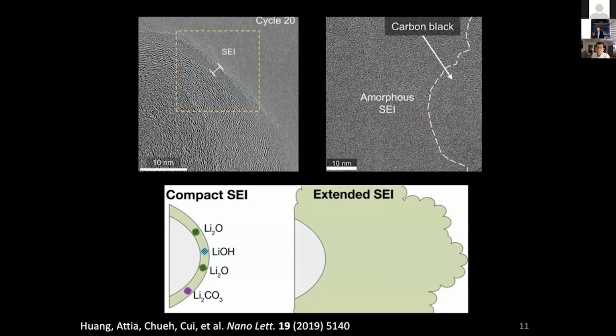If you now go to the atomic scale, we can use cryogenic electron microscopy, for example, to look at the interface between the liquid electrolyte and the negative electrode. In this case, this is the so-called SEI that is between the electrolyte and carbon. And you can see this is on the order of a few nanometers. And this is also something that changes as the battery cycles, going from something that's quite thin and compact to something that's quite extended and amorphous. And this contributes to the degradation of the battery.